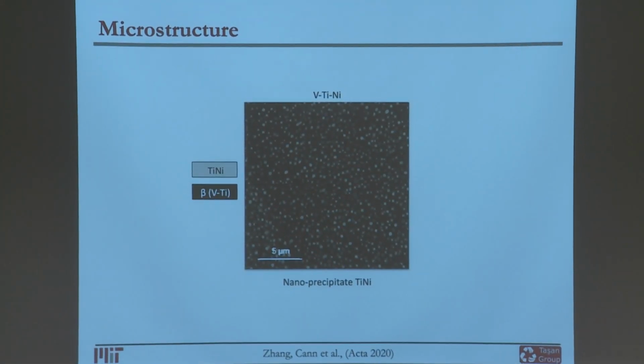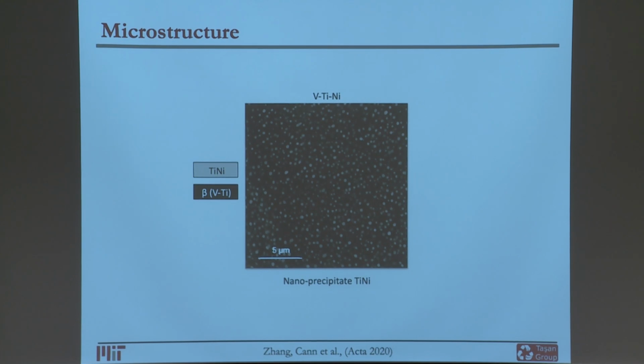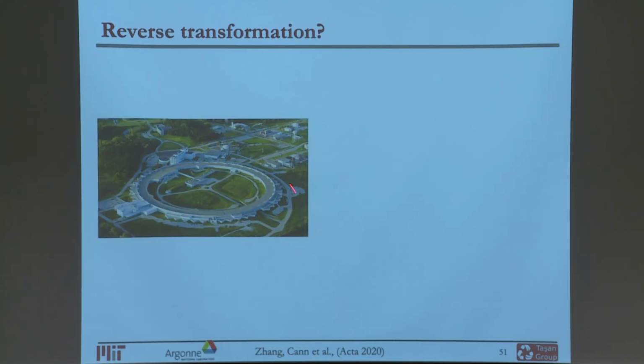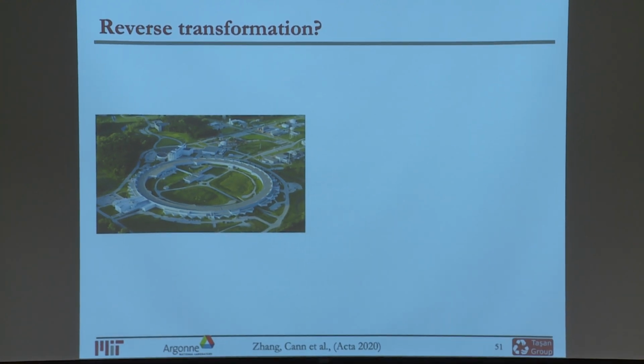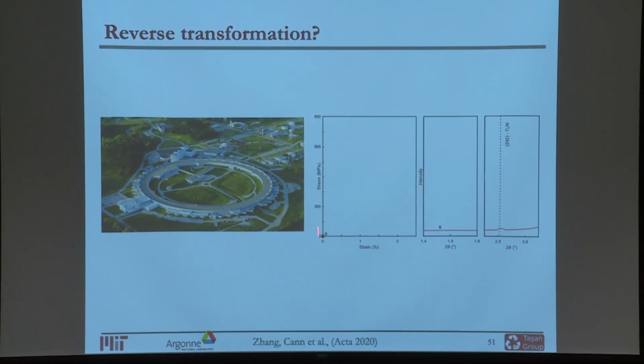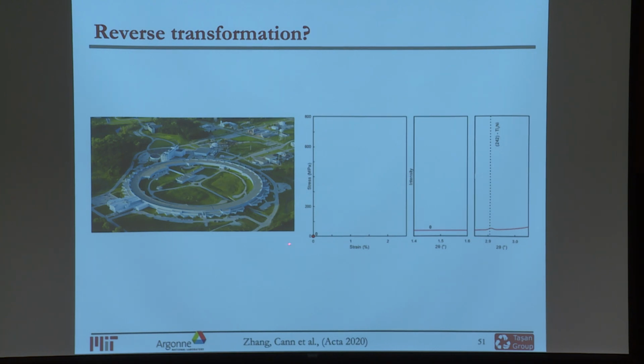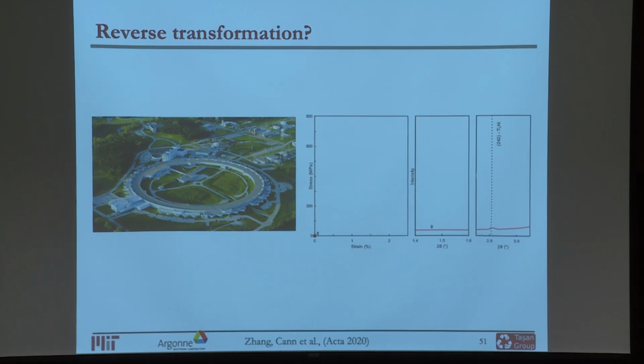But how do you even prove that it works? It's not so easy, actually, to show these transformations. First attempt, you can go to a synchrotron. We talked about in situ measurements in a synchrotron, and you can do a deformation experiment. Here in the y-axis you have stress, x-axis you have strain, and you are looking at certain peaks that are going to represent this kind of transformation. So you load, unload, load, unload. You want to see the forward signs of the transformation taking place and the reverse transformation taking place. All right, so we load it. So we go from 0 to 1.